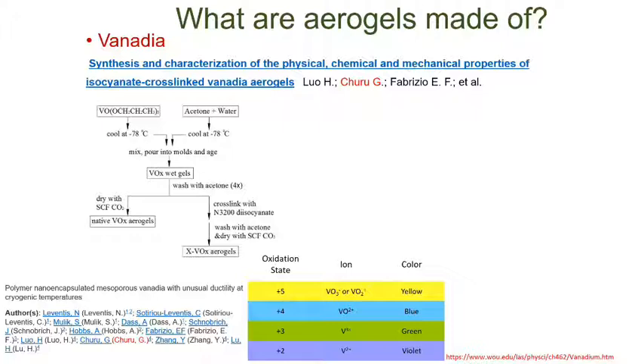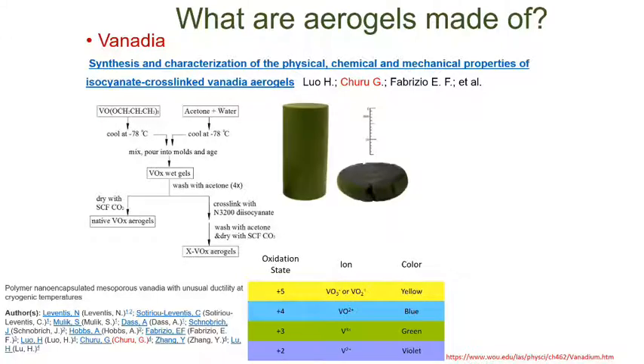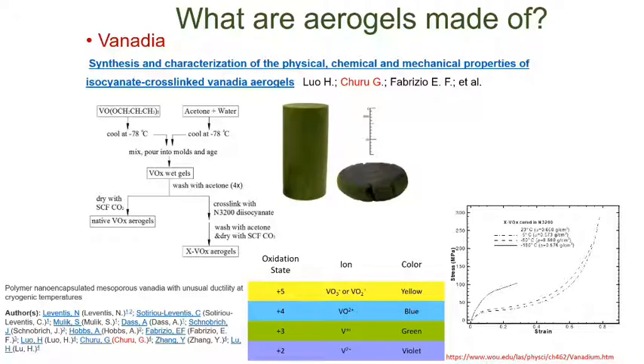The other material that we have worked on is called the vanadium aerogel. This is the material that we went to work with at Ames because we wanted to use it for catalysis. And again, the process is very similar to what we did with silica. And again, we did some compression tests. And as you can see, we can compress it to a very high percentage. And then we tested it at minus 180. When we do the test at minus 180 degrees, we got this really good curve, meaning that we can actually use this for installations when the temperature is really, really low.